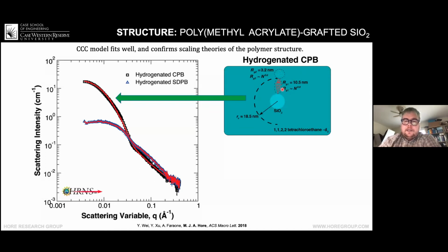So we were able to see very clearly that the radius of gyration of this inner region here was about 10 nanometers. It's really small here, but the scaling exponent was about 0.8, which indicates that the chain in the inner region is actually highly stretched, like we anticipated. And the cutoff distance between the concentrated and the semi-dilute polymer brush regions was about 20 nanometers, 18 nanometers. Just based on our rough estimate, we figured that this was about 15 nanometers. So our estimate was off by 3 nanometers or so. So not too bad. Finally, we were able to see a little bit of the polymer chain out here, but the scattering was very weak, but it had a smaller size of 3.2 nanometers. And if you remember, the molecular weight of that outer block was actually quite small. It was 6 kilograms per mole.